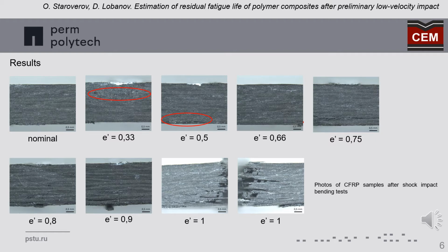Microstructural studies and analysis of fracture patterns of prototypes under complex shock impacts and cyclic loads were performed using a stereo microscope. When impacts with energies of 0.33, cracks formed from contact with the striker near the surface on which the impact was struck. While on the front and back sides of the samples, cracks, dents, chips and other types of damage that can be detected by visual inspection were not observed.